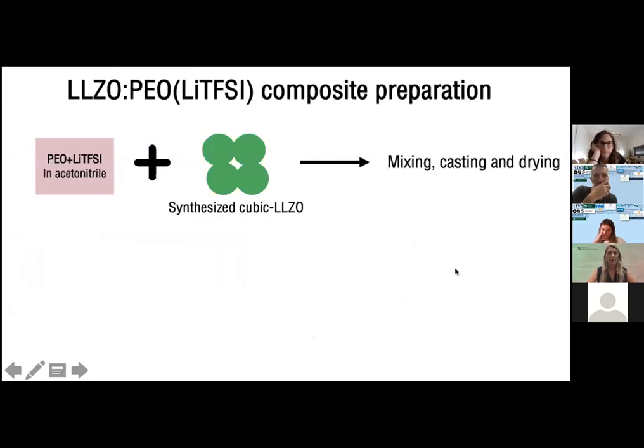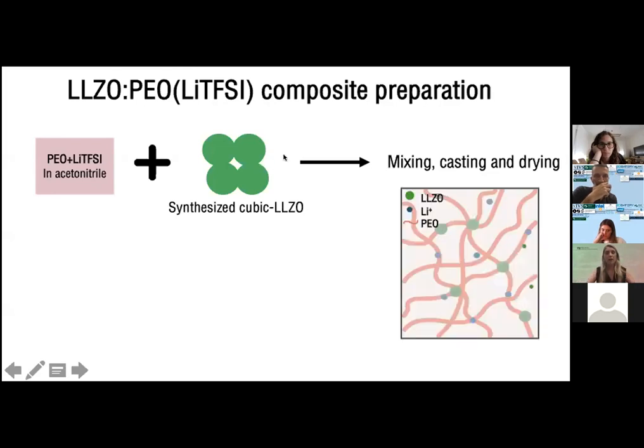So how we prepared our samples: we synthesized the LLZO, mixed it with the polymer and the lithium salt, PEO and lithium TFSI, cast the mixture and dried it. This is a schematic representation of how it looks: the polymer matrix here and the LLZO embedded in it. And this is how it practically looked, it's very flexible and robust.